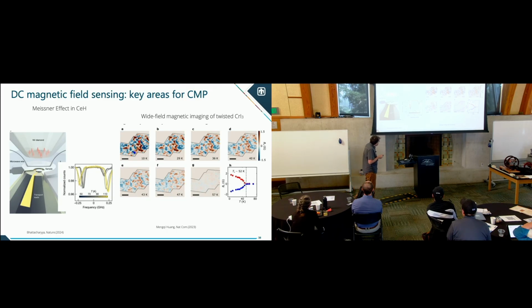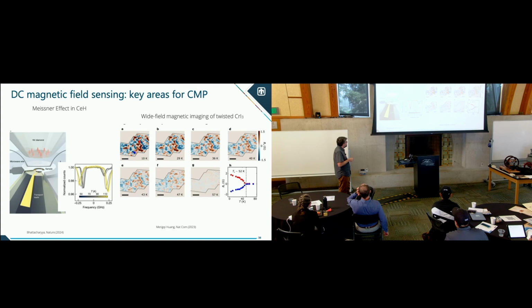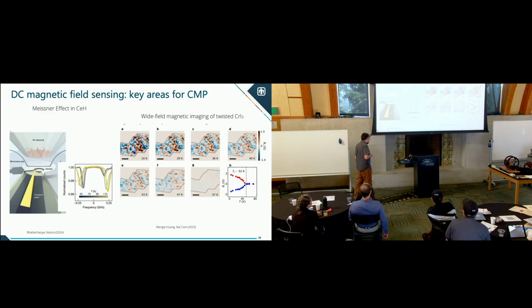But in the last 5 years, people have been pushing towards integrating nitrogen vacancies on the surface of one of these diamond culets. You press it down, and you're right next to the sample now. And at high pressures, up to hundreds of gigapascals, you can actually measure magnetic fields. This is from Norman Yao's group, and they're looking at some of the hydride superconductors, which have extremely high superconducting transition temperatures, and they see variations in the magnetic field. They can map out the Meissner effect in these materials. This is an emerging area where we're recently demonstrating sensing at high pressures too, and starting to integrate with materials.